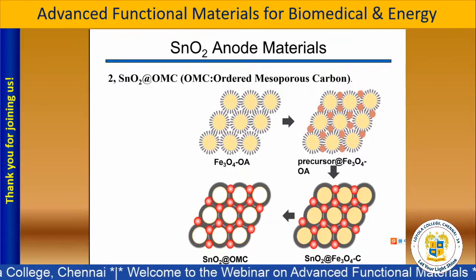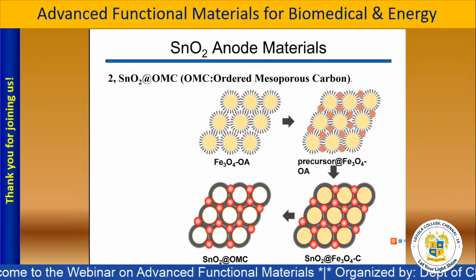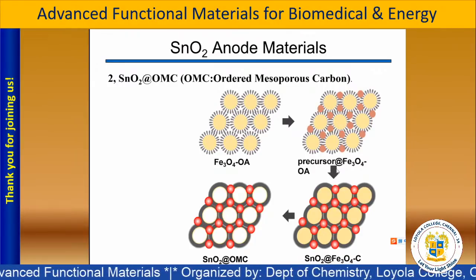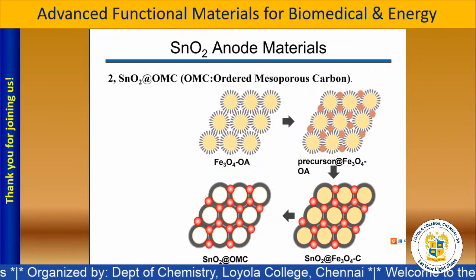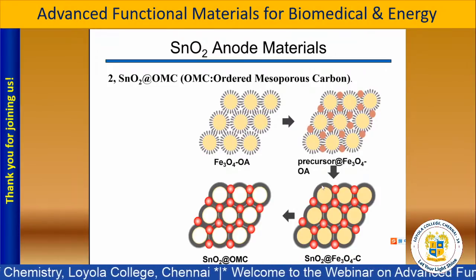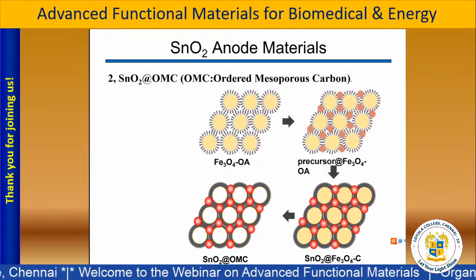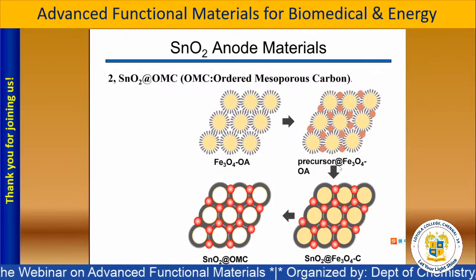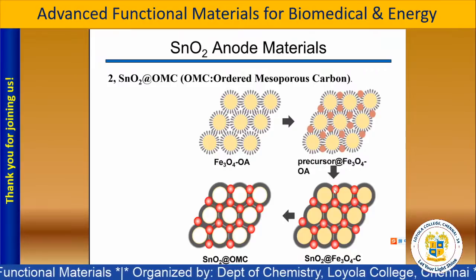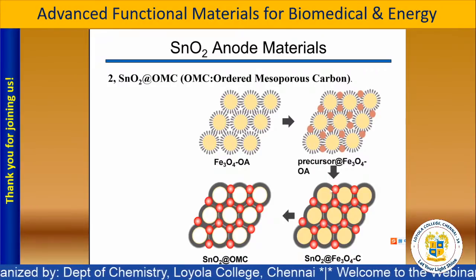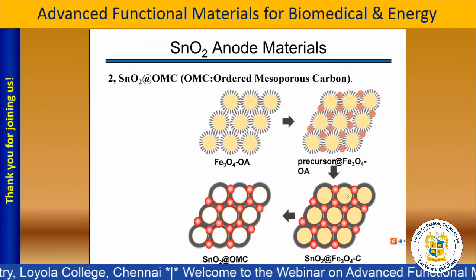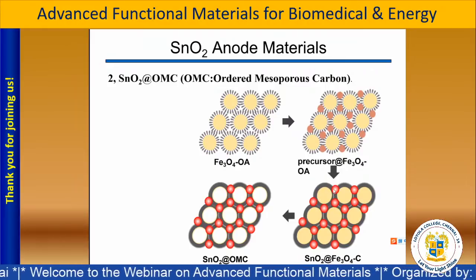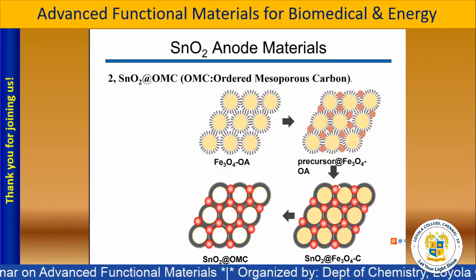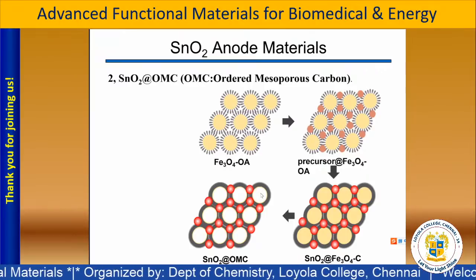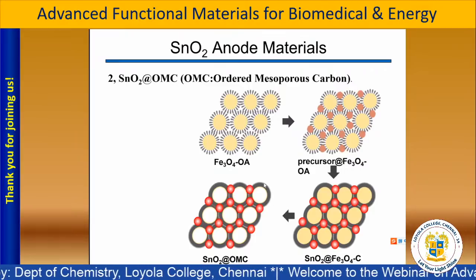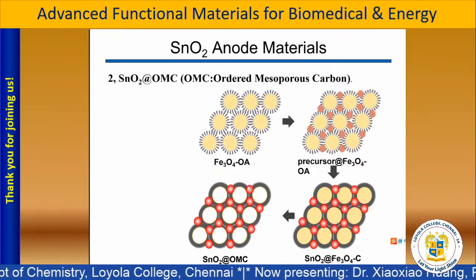When we get this orderly arrangement structure, we add the tin ion into this material, and then apply a heat treatment process. After heat treatment, we can see that the ferroferric oxide surface is covered by a layer of carbon, and the tin ion is transformed into tin oxide, and the tin oxide exists on the surface between the two ferroferric oxide particles. So the size of the tin oxide will be controlled. After the ferroferric oxide was removed, we can get this hollow carbon with ultrafine tin oxide.